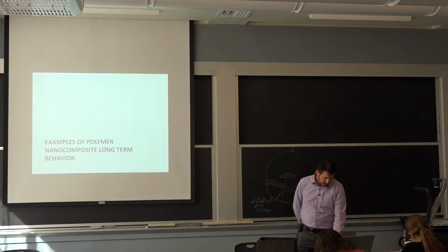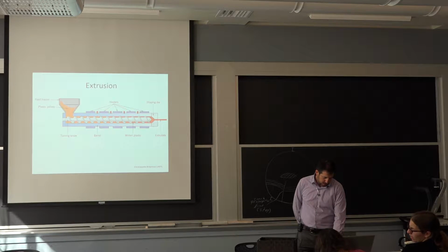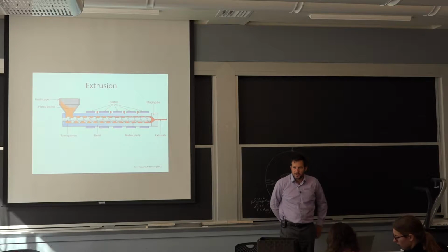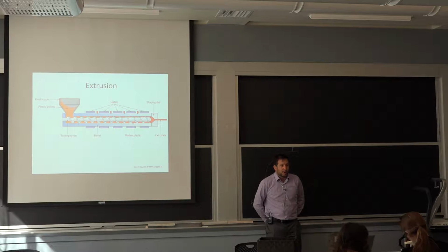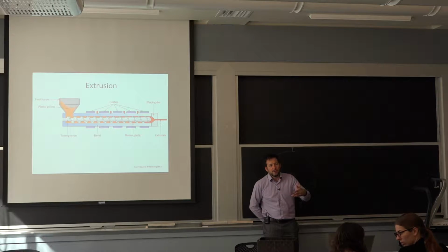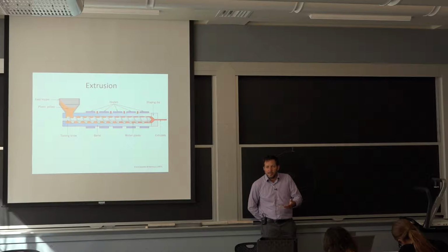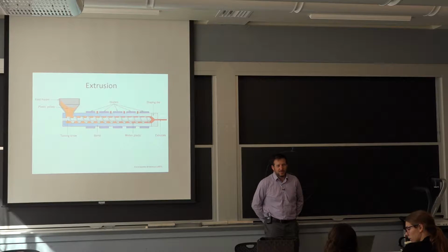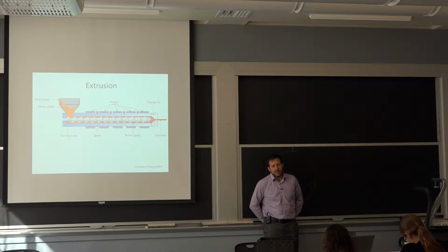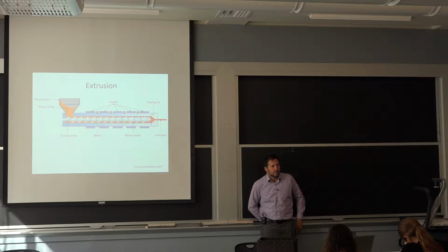So it's been a big adventure. The companies that sold all this system, of course, didn't know all the problems they were going to have. And then when you start having trouble, sometimes it takes a little bit of time to realize, well, okay, it happened to this person. Maybe they really put some strong chemicals in the pipe, and then you start having 10 calls and realize, oh, we have a problem. So now you start making changes, but it takes a lot of development. I mean, these tests at 10,000 hours to know if you started initiating cracks with one compound and then you do it with another compound, and what else can be in there, even from the water